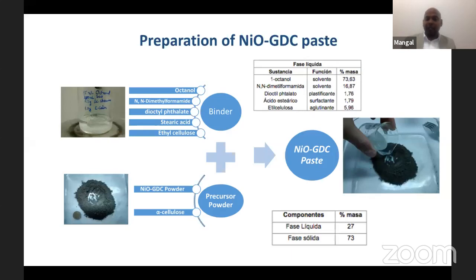For that paste, we need to add different materials, for example, different binders, to make a pasty kind of nature so that it is easy to extrude the powders. As for how much liquid phase and how much solid phase was present in the composition, you can see about 27% liquid phase and 73% solid phase was used to prepare the paste. Of course, we use octanol and dimethyl formamide, and this is the composition that we have chosen to prepare the paste.